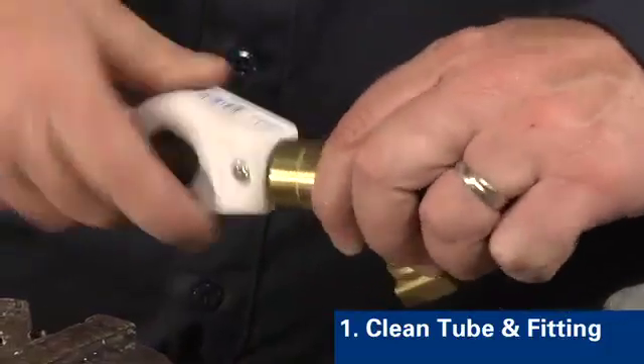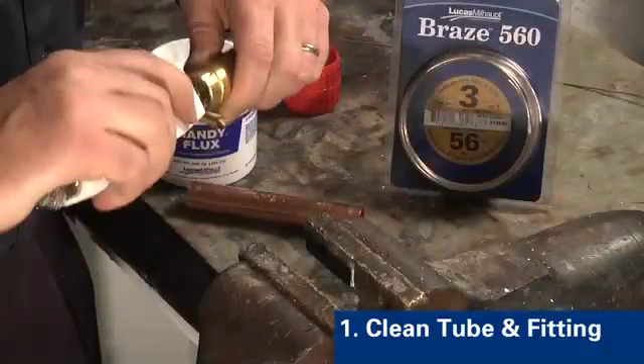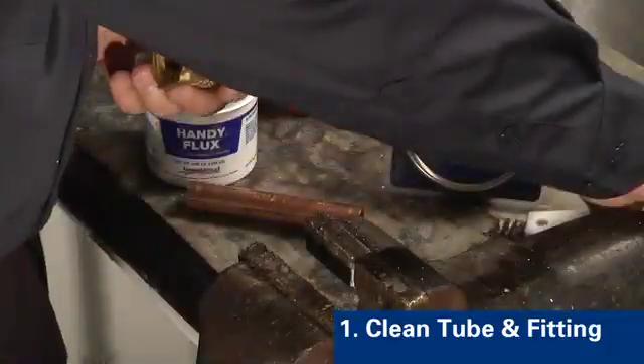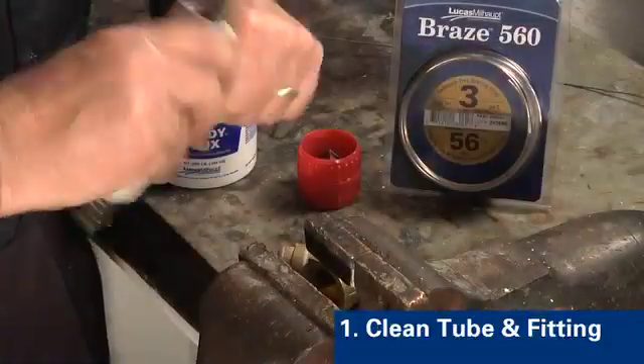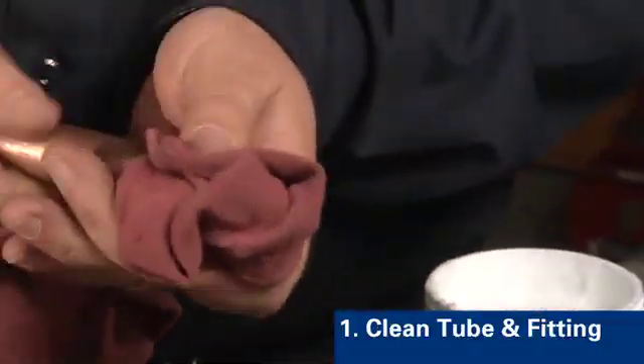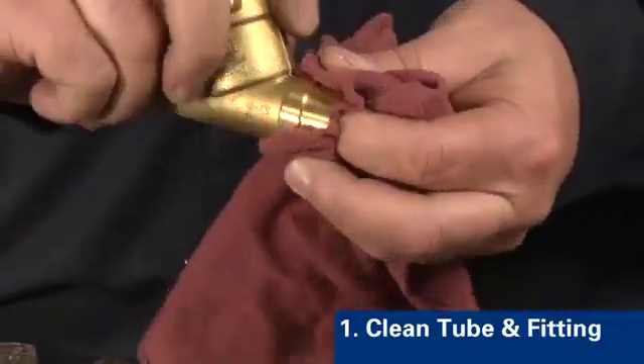Cleaning should be performed so that the surface contaminants are removed without unwarranted loss of the base metals. Lightly roughen the tube ends and the fitting with wire brushes, steel wool, or fine grades of abrasive papers. Any residual particles in the joint surfaces should be avoided, and any residue remaining after mechanical cleaning must be removed.